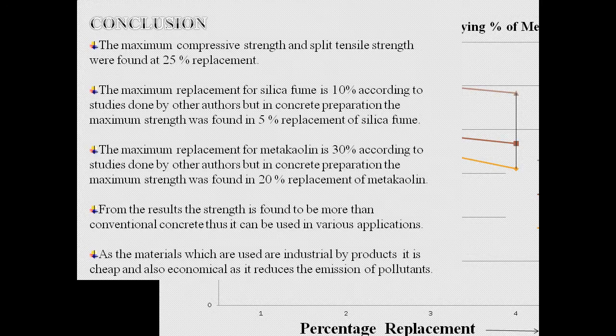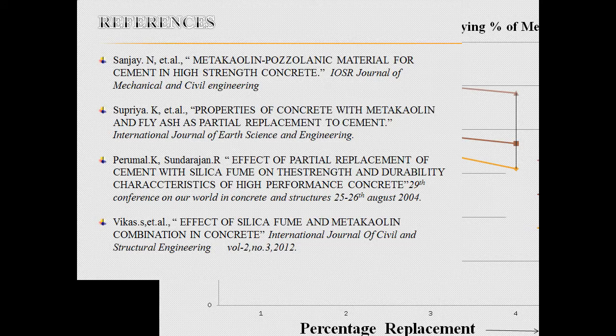Then we have given the conclusion. The maximum strength is around 25% replacement. As you can see, the maximum replacement for silica fume is 10%, but in our project 5% is the maximum replacement. The maximum replacement for metakaolin according to studies is 30%, but we are considering the maximum strength to be at 20% only. From the results, the strength is found to be more than the conventional concrete. Thus, we are reducing the pollutants and also increasing the strength. These are the references.